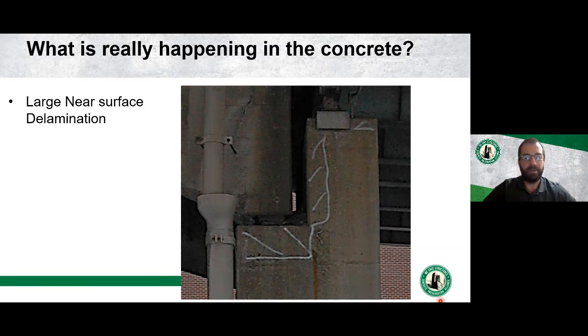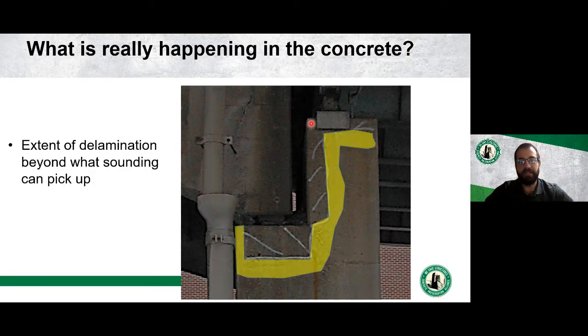But is that the only thing that's happening there? Well, we probably have delamination and debonded concrete that extends beyond that white hatched area, right? If we took a chipping hammer to that white hatched area, we all know that it's probably going to grow in size because there are areas of that damage area that we can't identify with hammer sounding alone, right? There's micro cracking and smaller delaminations that exist beyond that white hatched area that, when we take a chipping hammer or something physical to it, is going to open up. So if we just went with the quantity of area that was identified by the white hatched area, we're probably greatly underestimating the proper repair area.